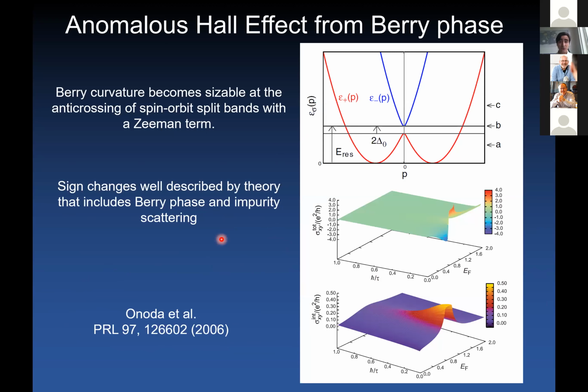And the minimal model to characterize this type of behavior was discussed in this paper. So here you are considering a Zeeman split system with spin-orbit coupling, in which there is an avoided level repulsion around the gamma point. And a sign change of the Berry curvature, and therefore of the anomalous Hall effect, is described by the theory that includes both this type of electronic structure and impurity scattering.